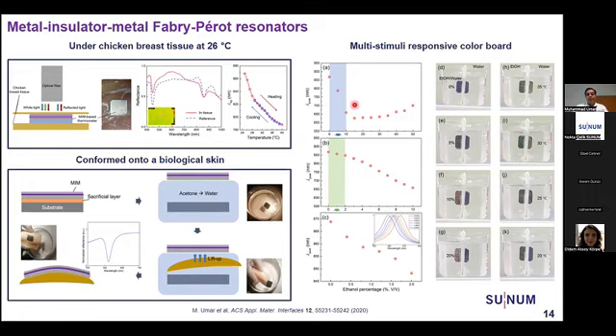So we checked the amount of alcohol in water. Initially, here you can see the response of the device from 0 to 50%. First, the resonance shift in water at 0% alcohol, and when the alcohol concentration increases, the resonance shifts to a lower wavelength. A very low amount of alcohol in water could be sensed, like 0.5%. Up to 15%, the alcohol starts collapsing the structure of the polymer, and after that it behaves in an opposite way and starts demixing the polymer.